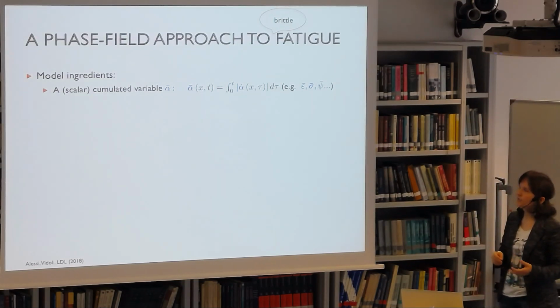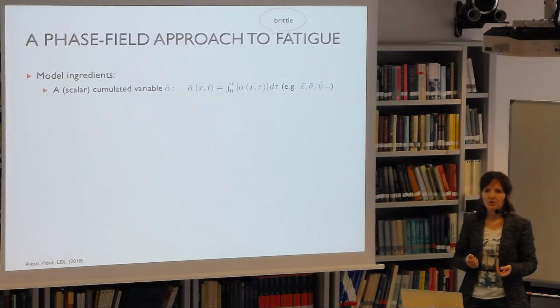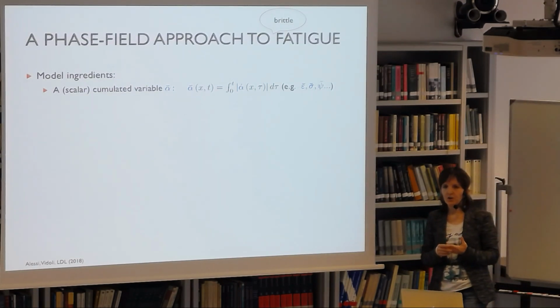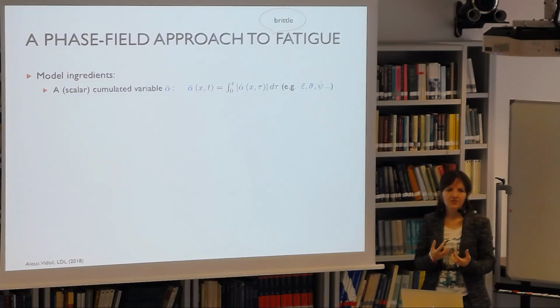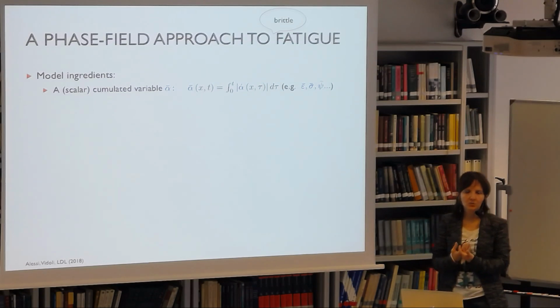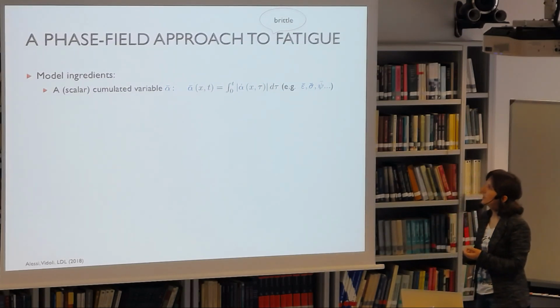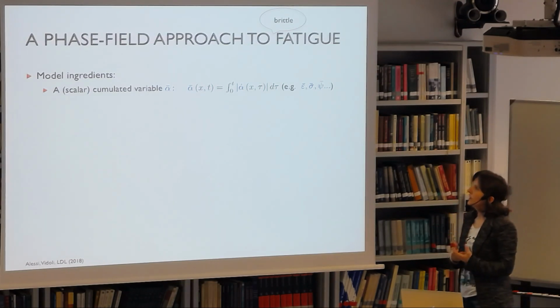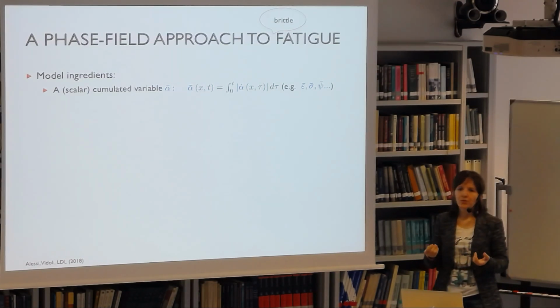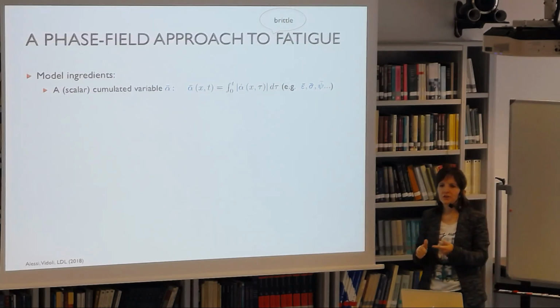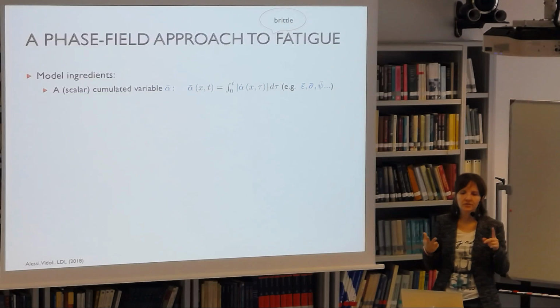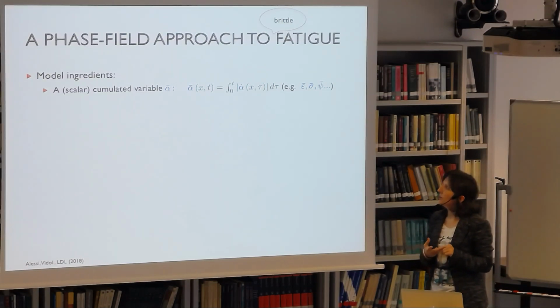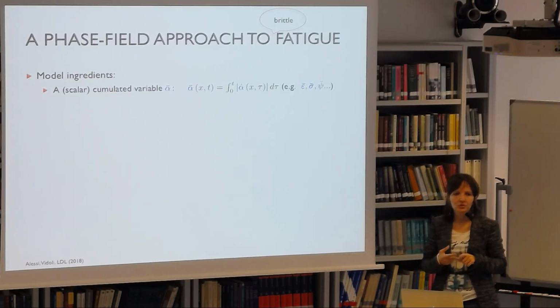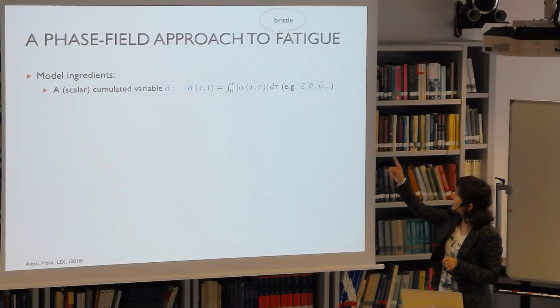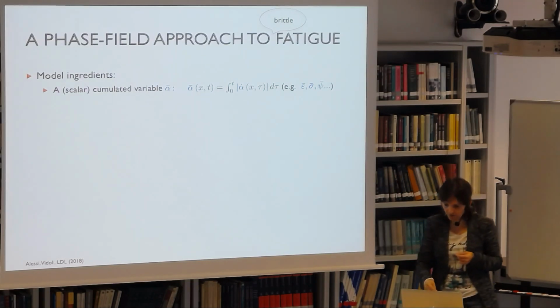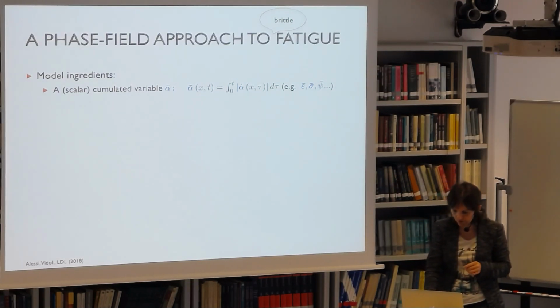What are the ingredients of this fatigue extension? Well, first of all, we need a variable that tells us what is the mileage of the material, so how strong the fatigue effect is. So we need a cumulated variable that we treat as an internal variable, and I'm putting it there in a very general form. In the beginning, we thought this could be any scalar measure, for instance, of strain or of stress, or for instance, the elastic strain energy density. But I'll show you very soon that not any of these choices is good. And in particular, I'll show you that out of these three options that I'm writing there as examples, only the second and the third are possible choices, and the first one is not good.